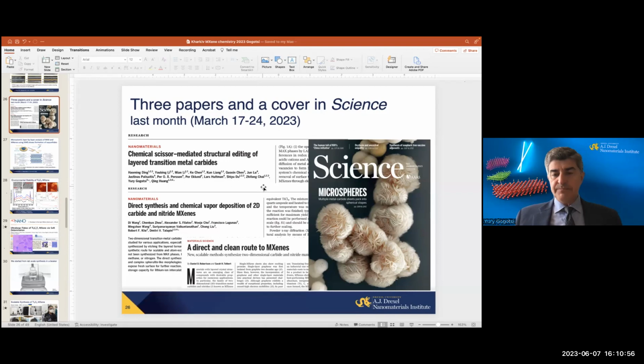I'm not an expert in CVD or PVD, but people grow cubic carbides, and people grow MAX phases by magnetron sputtering. So I think PVD, CVD techniques, and atomic layer deposition with annealing should work here. It's just a matter, again, of someone going to the lab, setting it as a goal and making it happen. People grow 2-3 nanometer films of Mo2C, for example, so it's possible. It's just finding a way to make the process self-terminating after a monolayer or two, preventing random growth and thickening of the film.